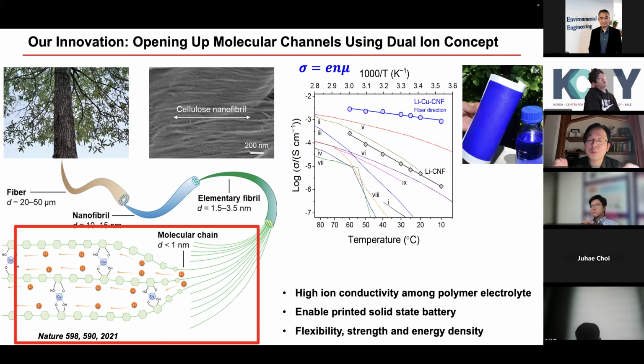And the distance between the molecular chains is not that big. So the ion can transport very quickly between the molecular chains. That means a very high mobility. The number N times mu gives you very high ion conductivity. So we actually get almost the record high ion conductivity in a dry wood fiber.